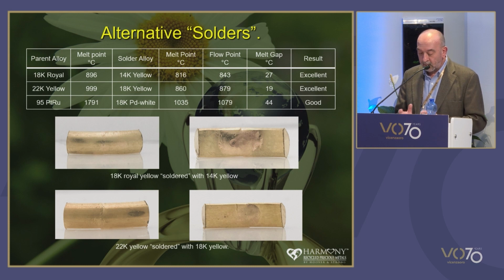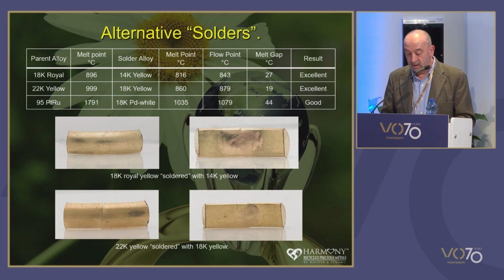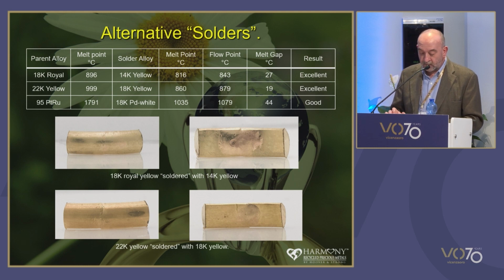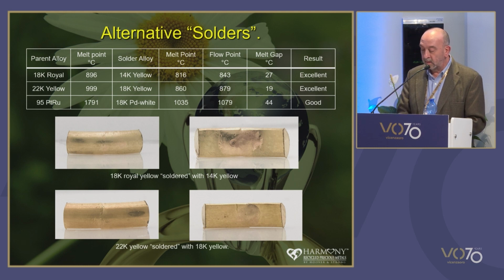A little bit not so good on the 18 palladium white doing the platinum, but those results were also acceptable. So this really showed us that you do not need special solder formulas for things to act as solders. All you need to do is fill the criteria and the operation should work.